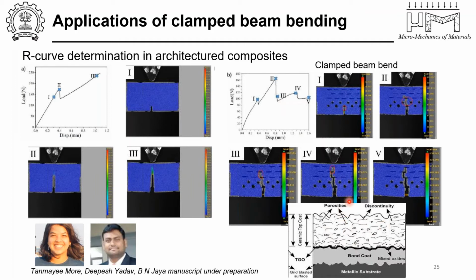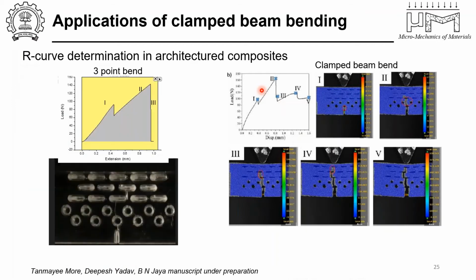And we wanted to see what happens if you just create these holes, because this will make my material less dense. But what it is clearly showing is that the crack grows in one shot for the bulk solid beam, whereas if I have an architecture beam, then I see a number of load drops, corresponding to which I see the cracks deflecting and blunting and so on. So I achieve a much higher fracture energy before it completely breaks. So the damage tolerance is improved when I make these architecture composites.